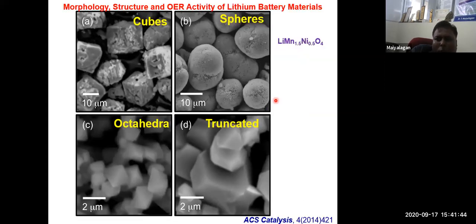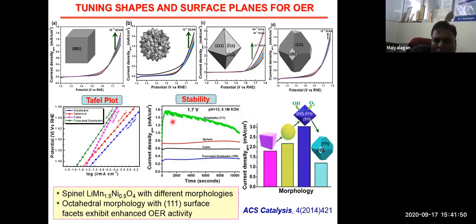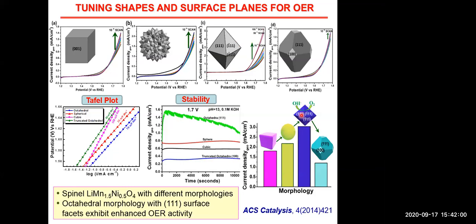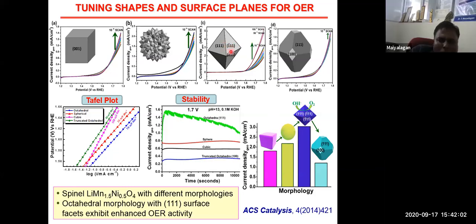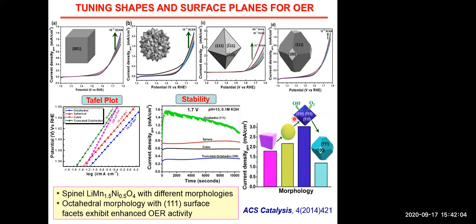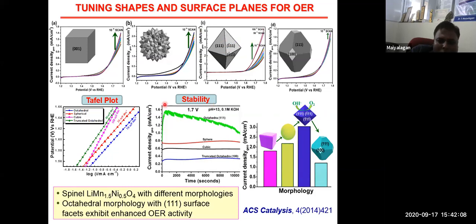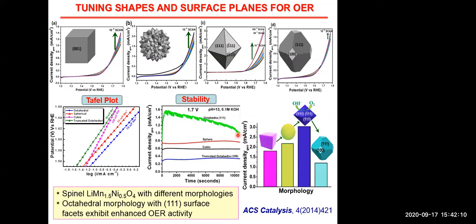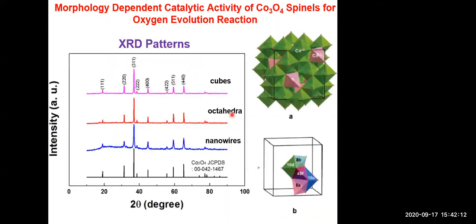We also took lithium battery materials like cubes, spheres, octahedra, and truncated octahedra, to see whether morphology and crystal planes play a major role in OER activity. We found that the 111 planes, which are exposed more, expose more active sites. So for this particular material, the 111 plane shows better activity. It varies based on the material.